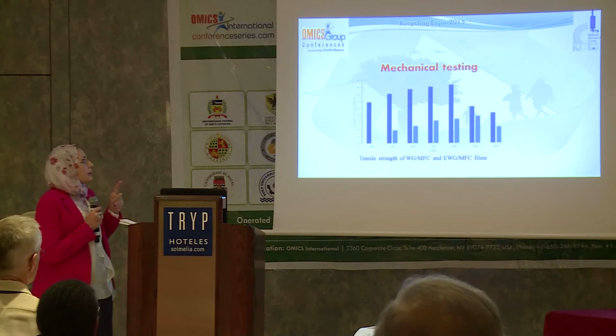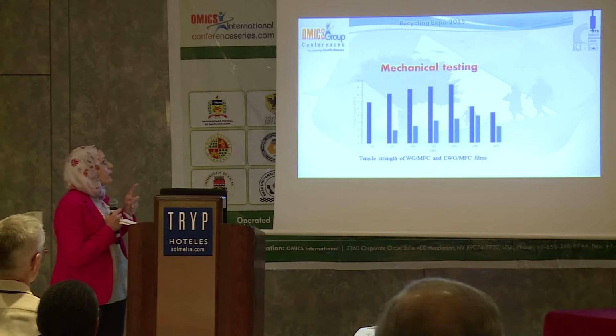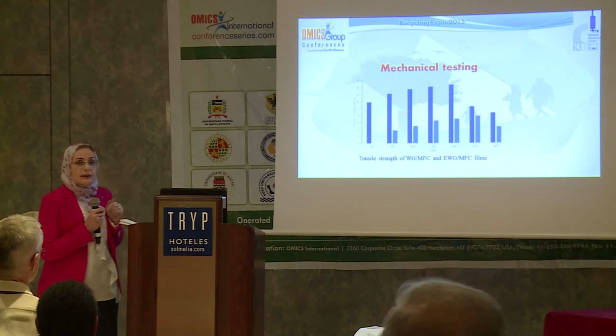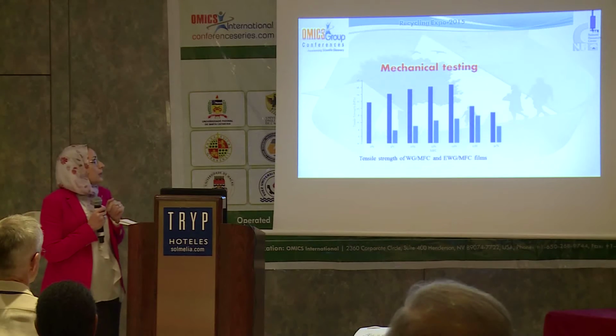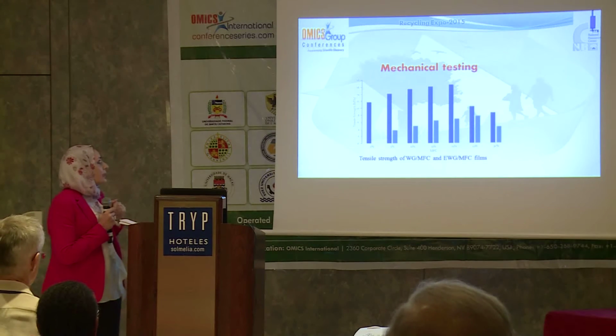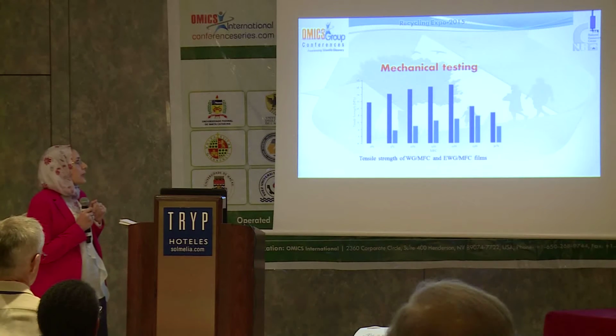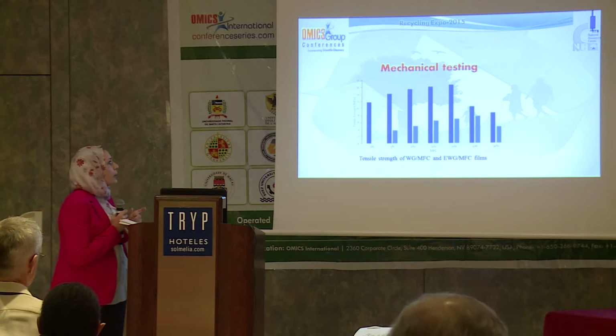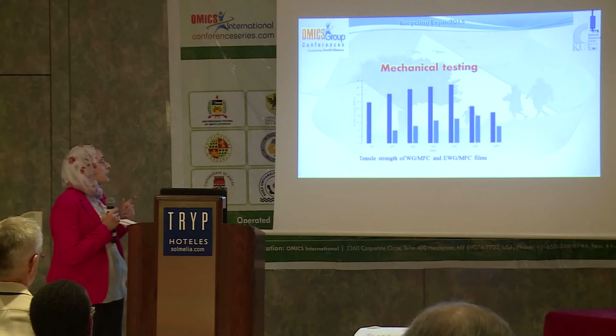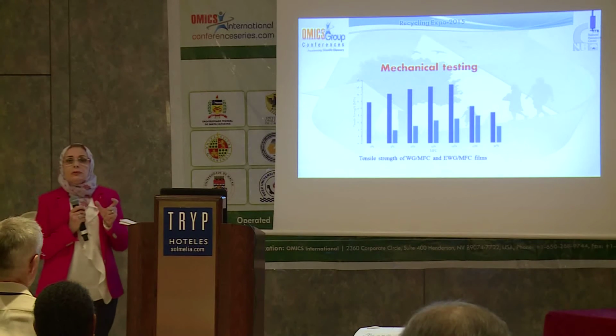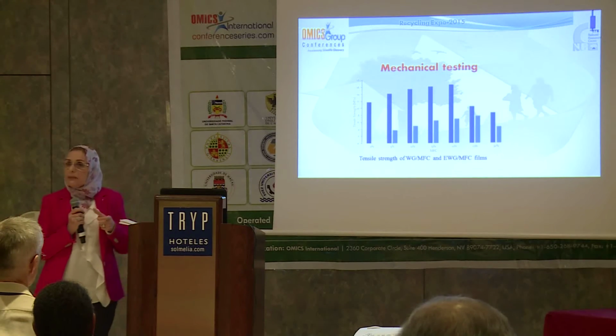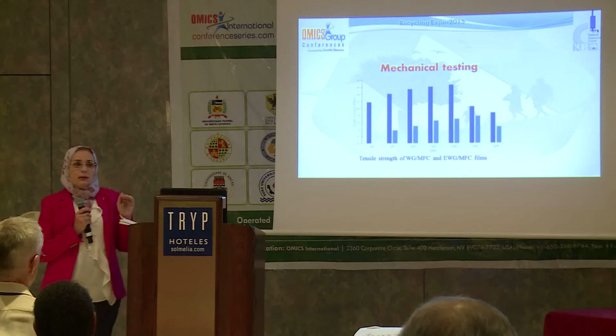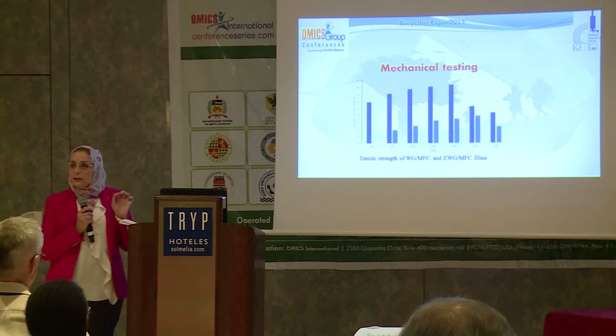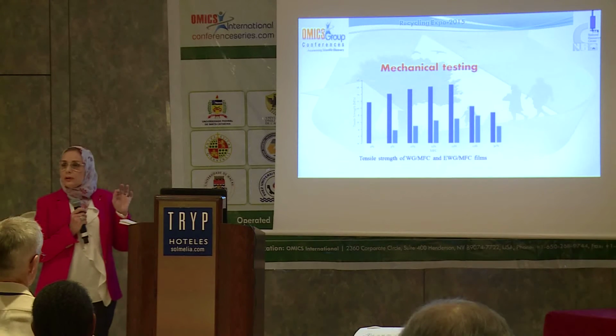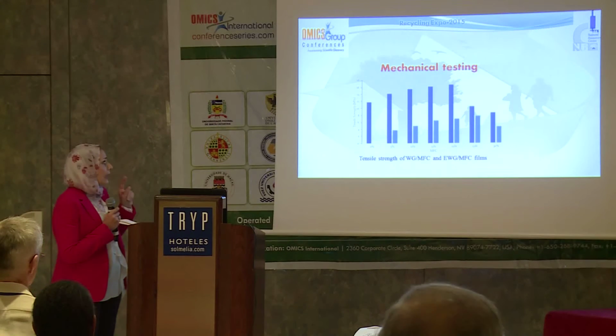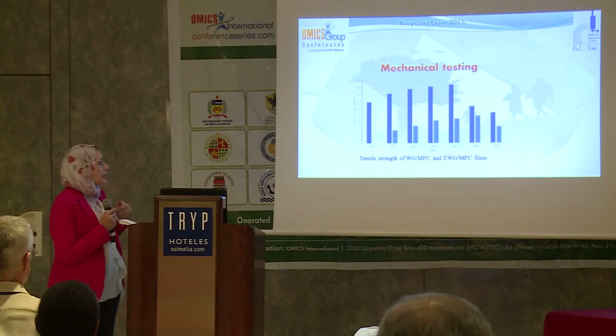As we can see, chemical denaturation was better than enzymatic denaturation. I think that the hydrolysis of the wheat gluten resulted in low molecular weight wheat gluten, which was unable to make a good film, and the chains did not arrange in a good manner to produce good films. And the chemical denaturation was better.